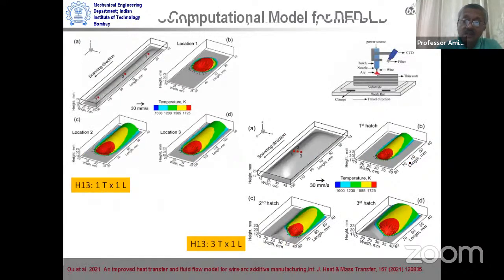So this will help us not only in the laser engineered net shaping process, even if we think of gas metal arc based directed energy deposition process like this one, right? In this case also, these models are now developed, which are well established. For example, to create layers by this kind of GMA process, and whether it is one track, one layer, three track, one layer, these models can actually predict what would be the shape of the profile of the deposit and how the temperature profile or melt pool or the track profile will be asymmetric as we move from one track to the neighboring tracks, which is intuitive, but we don't know how much it would be unless we do trial and error studies. So one alternative is this one, where we can reduce the number of trial and error much lesser.